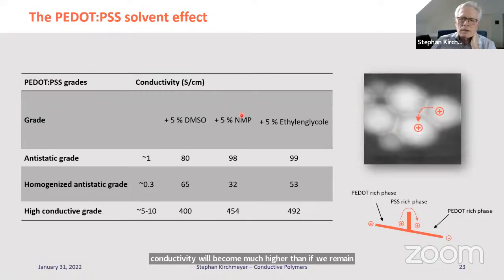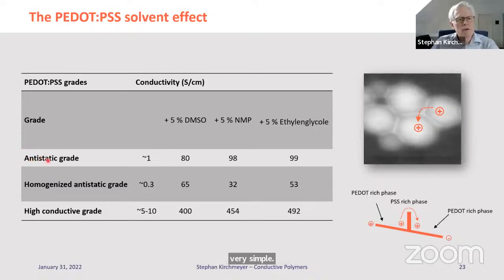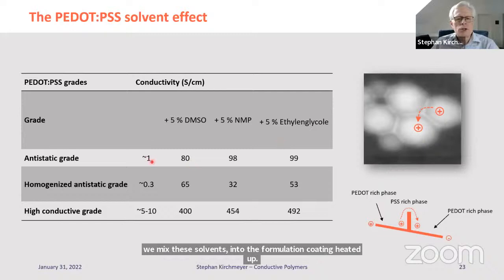And what's happening with certain solvents, with very polar solvents like DMSO, N-methylpyrrolidone, or ethylene glycol, is that these solvents are able to dissolve this layer in between and get the PEDOT in these particles to interact much better. It is some sort of recrystallization process, and sometimes in a microscope it can be even seen. But the macroscopic effect is very simple. If we take various grades that, for example, can be bought on the market and measure their conductivity just by making a coating and measuring, then we measure values of 1 or let's say a maximum of 10. If we mix these solvents into the formulation coating, heat it up, then suddenly the conductivity jumps up by a factor of 100.